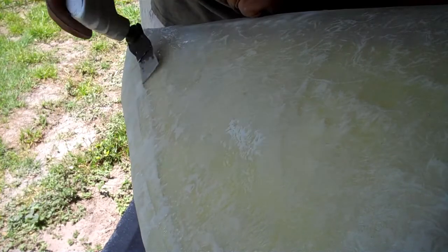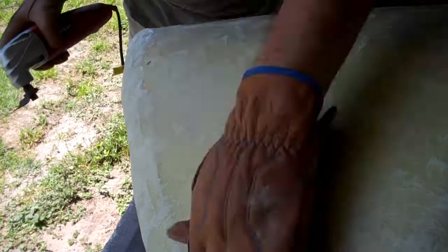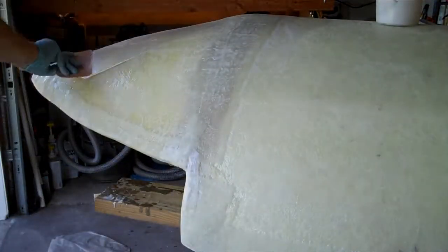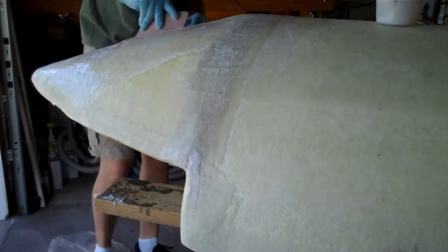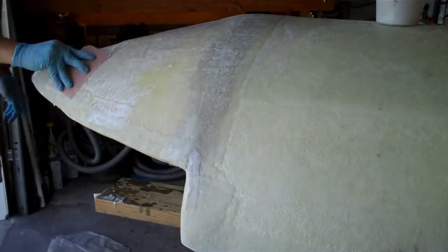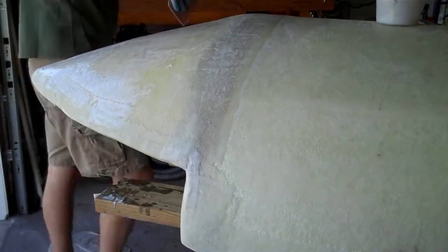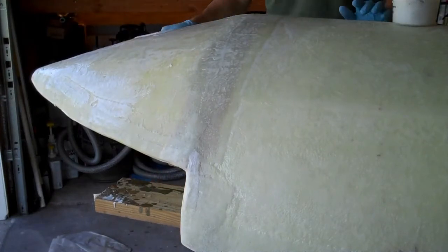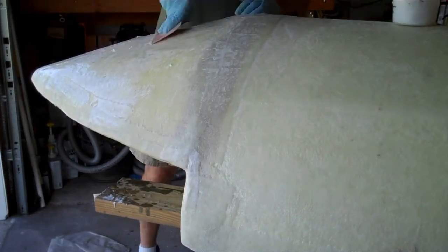After laying up several more layers on the nose cone, I flipped the entire pontoon over again and had to cut off a few pieces of the wraparound that didn't fully bond. After sanding, I'm using a 10% by weight microballoon glass bead and epoxy mixture to skim coat the chop strand mat nose cone and smooth things out to get ready for the final woven fiberglass cloth layer.